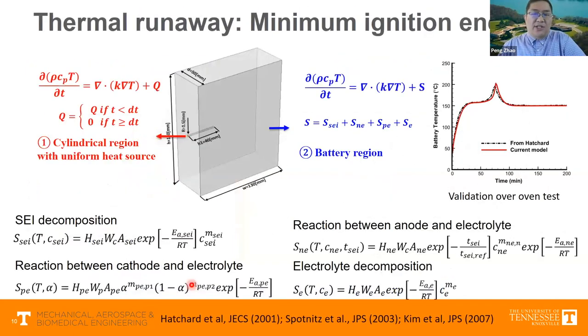And the model we established is rather simple. Assuming that this is a prismatic cell, then we can use a cylindrical region to mimic the heat release from a nail penetration procedure. For example, we can add an artificial constant heat source within the cylindrical region that mimics the nail. Outside of the cylindrical region, we can consider the thermal runaway chemistry.